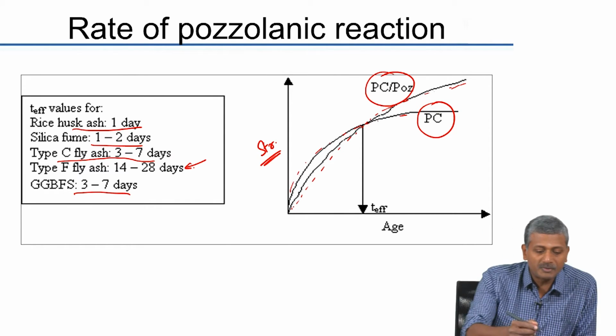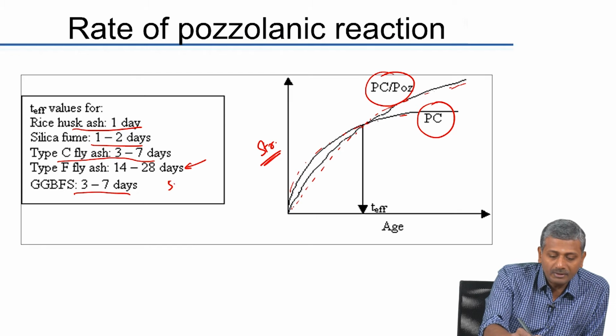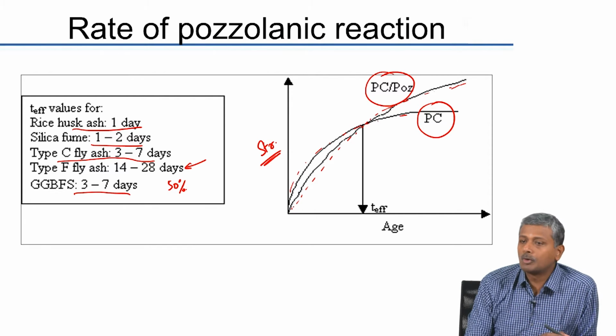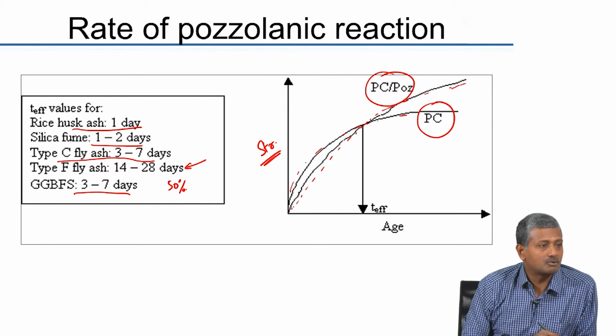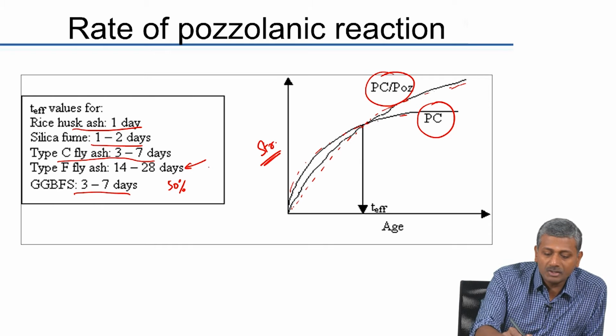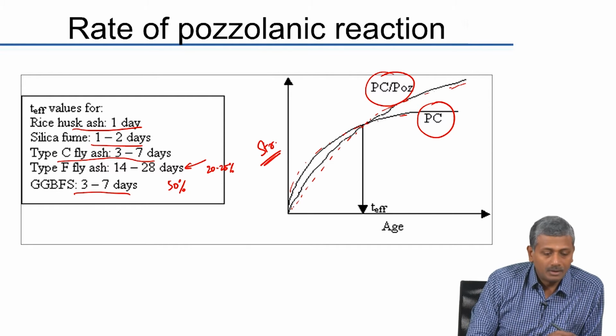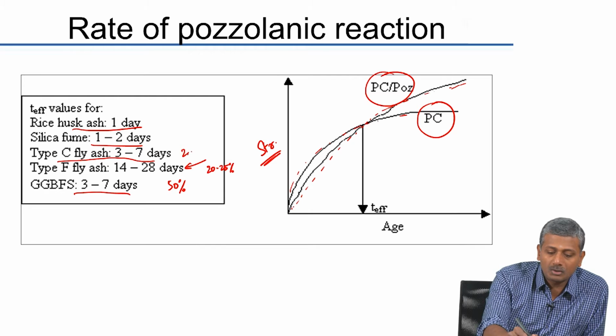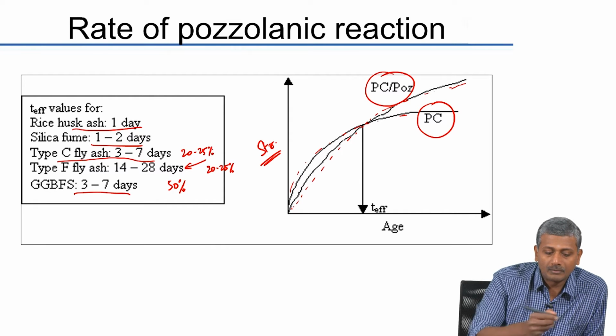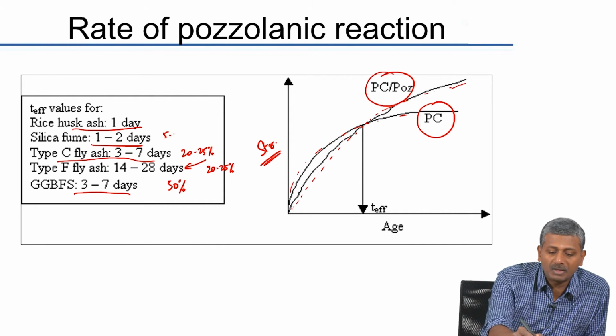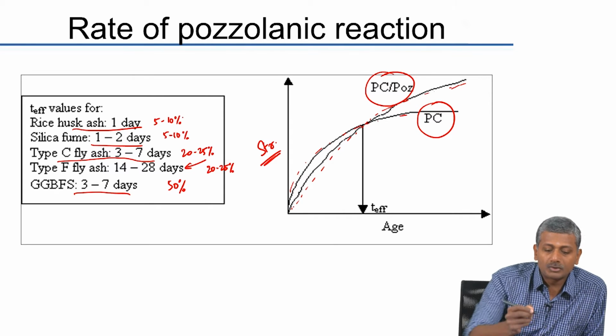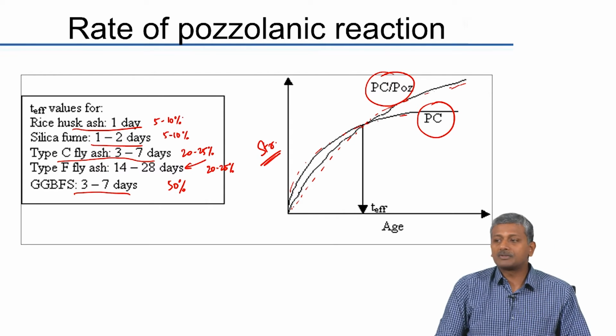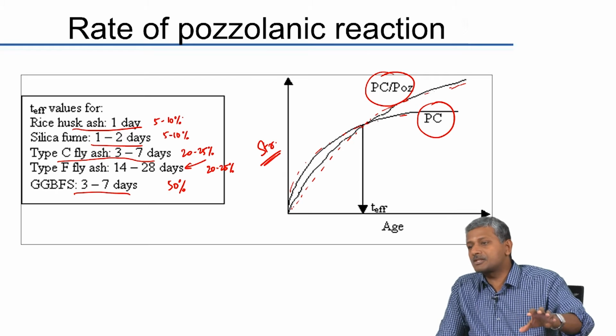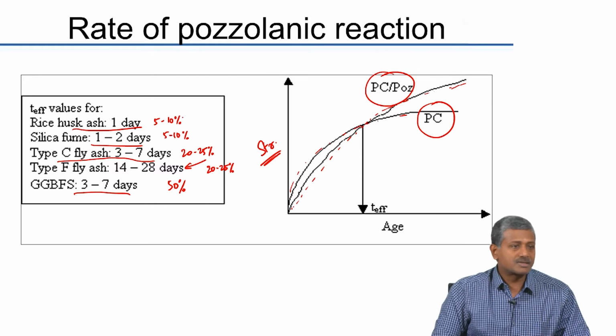What are the typical replacement rates? For slag, it is 50%. Please remember we talked about Portland slag cement, where slag is typically around 50%. Type F fly ash will be about 20 to 25%. Okay. Type C fly ash, again same 20 to 25%. Silica fume probably about 5 to 10%, and rice husk ash also 5 to 10%. So, those are the typical replacement rates of these materials. Now, why are these replacements restricted to these numbers? We will discuss that in some detail.